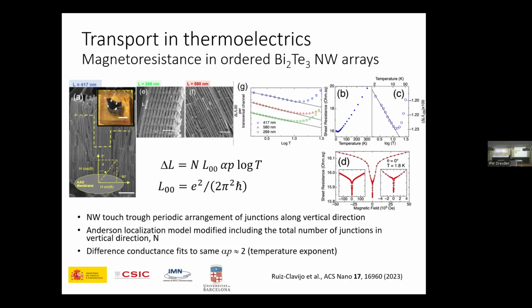Yeah? What we saw, we did several things, and to make the story short, the resistance follows the Anderson localization model in the transverse direction, which is partially or mainly due to confinement effects in these constrictions. And another thing that we saw, a little more interesting, is that the weak anti-localization feature in that nanostructure has a weird shape to it. You know? Usually with weak anti-localization you have maybe a parabolic shape, whatnot, and at some point you enter into the localization regime and you have one dip. In this case, there are two dips. You know? One, and then a second very pronounced.